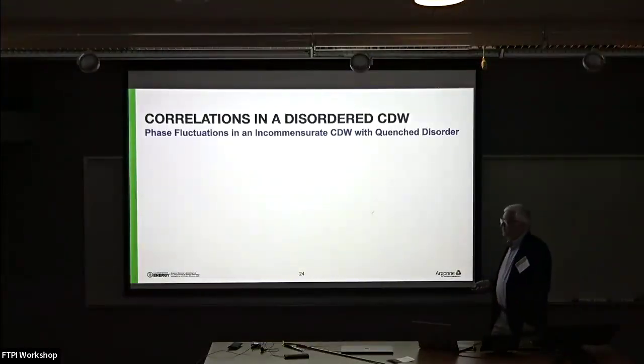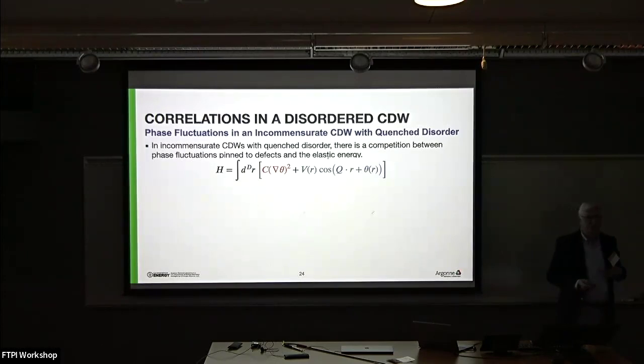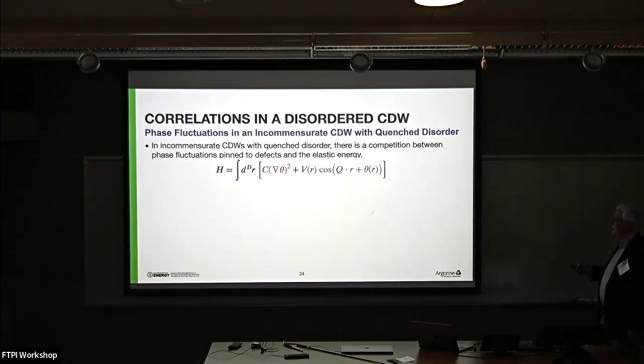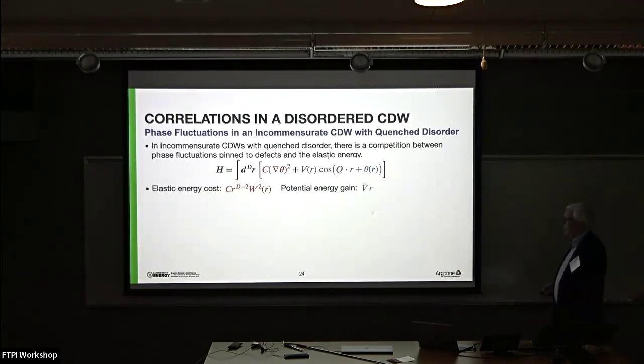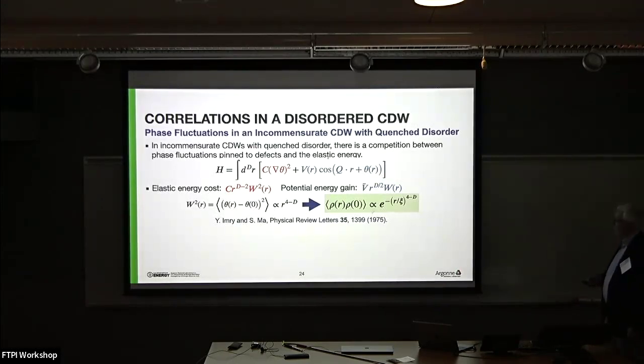So the origin of this story, in case you've not heard of Bragg glasses before, goes back to the 70s and the result from Imry and Ma that if you have an order parameter with continuous symmetry, it's unstable to arbitrarily small disorder. The idea is that you have a disorder potential which is trying to pin, in this context of a CDW, the CDW to the dopant, say, and you have elastic restoring forces that are trying to homogenize the phase fluctuations. If you optimize for those two competing forces, you end up with a density function with decaying exponentials. You basically have short range order below a couple of dimensions.